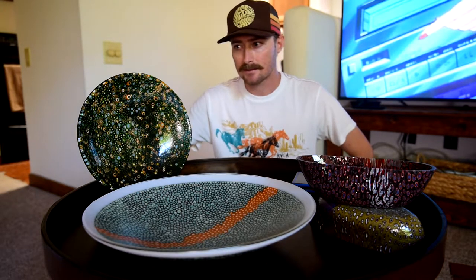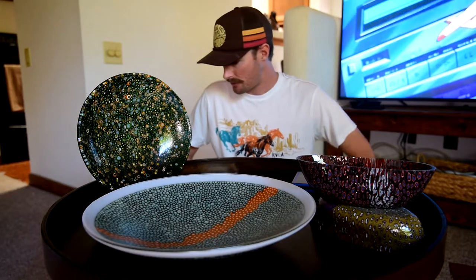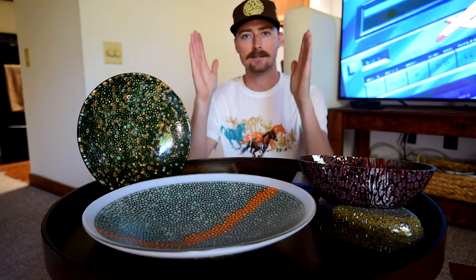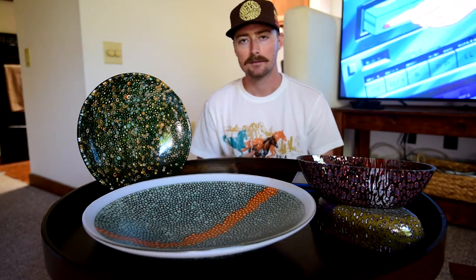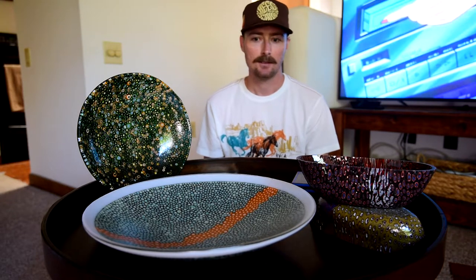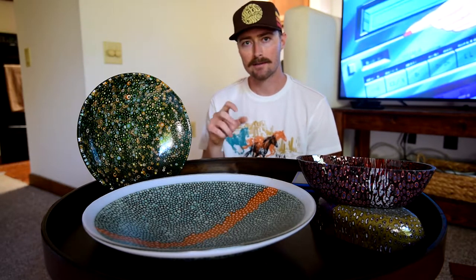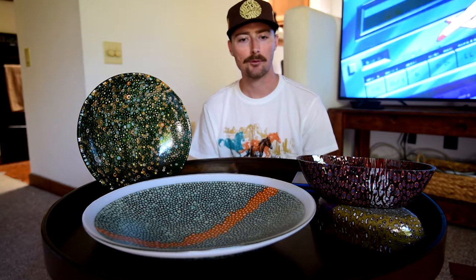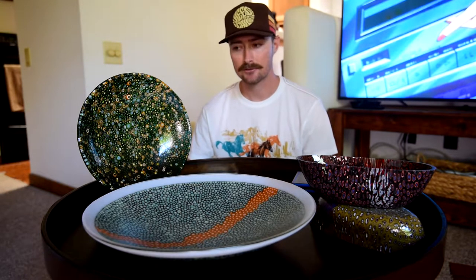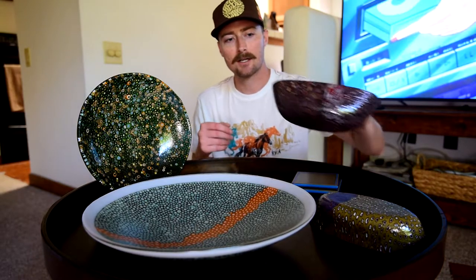And this glass comes from a kiln called the Vitrograph Kiln. It was designed by Rudy Gritch. It's a small box kiln. It's got an 8x8 inside, and there's a hole at the bottom. That hole at the bottom allows for the glass to be pulled out into strands. And the kiln is elevated, and when the glass is pulled out through the bottom, you get long strands, and then you cut it up into tiny pieces. And this is also a process that was first discovered in Murano in Italy in the late 16th century, an ancient process that I have just absolutely fallen in love with. And I want to talk about some of these considerations.